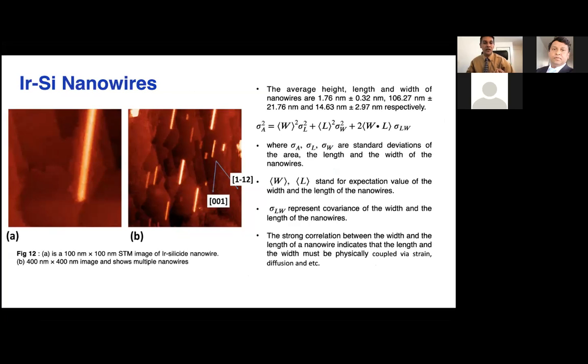We deposited a quarter monolayer of iridium, and we did the post annealing after that at around 600 degrees Celsius. Then after scanning tunneling microscopy imaging, we got this. In Figure A and B, you can see that nanowires formed on the silicon 110 surface. The direction of the nanowires is along the 0, 0, 1 direction.